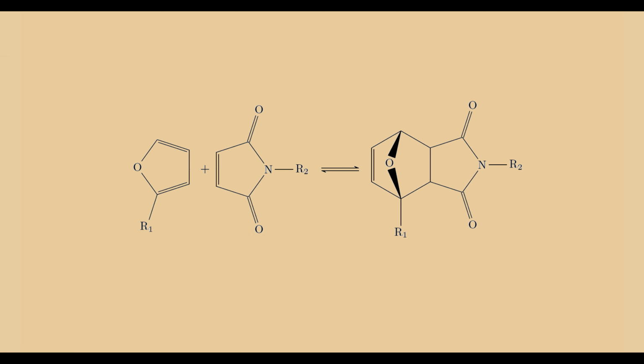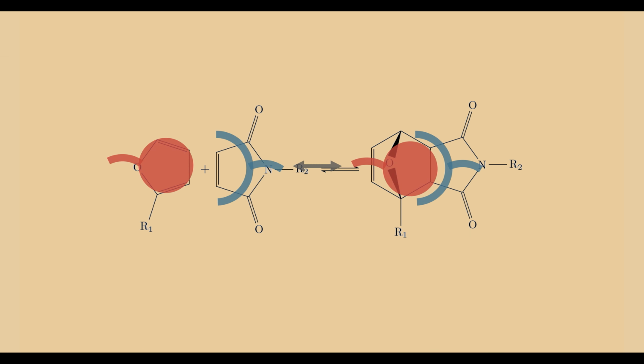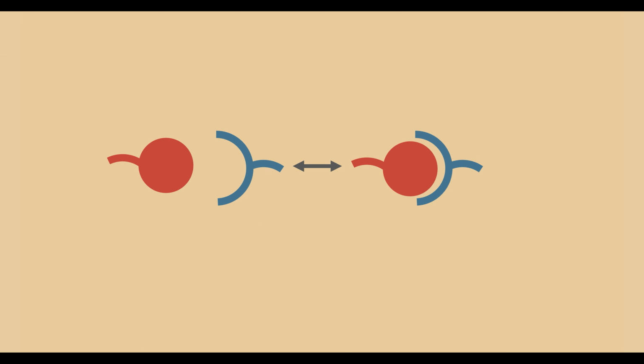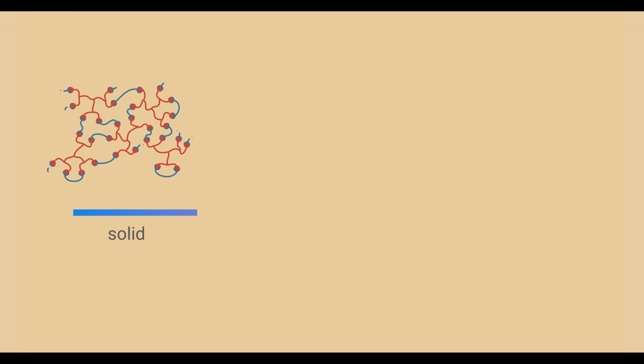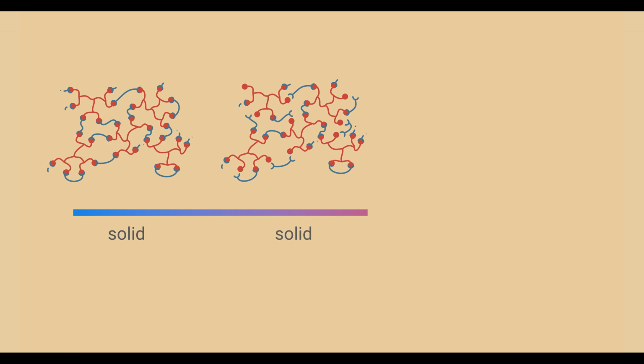These remarkable polymers rely on the Diels-Alder reaction. The Diels-Alder bonds serve as the crosslinks within the polymer network. And this reaction is thermally reversible, meaning that the crosslinks in the network can be formed and broken by changing the temperature. At room temperature, most of these bonds are formed. Upon heating, the equilibrium shifts, progressively breaking more and more bonds.